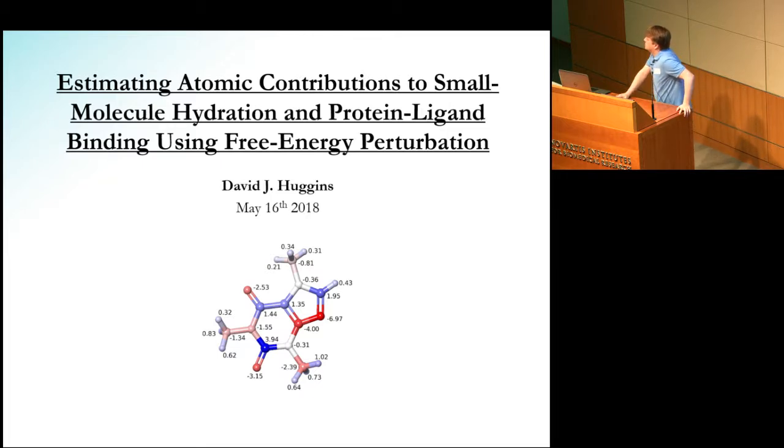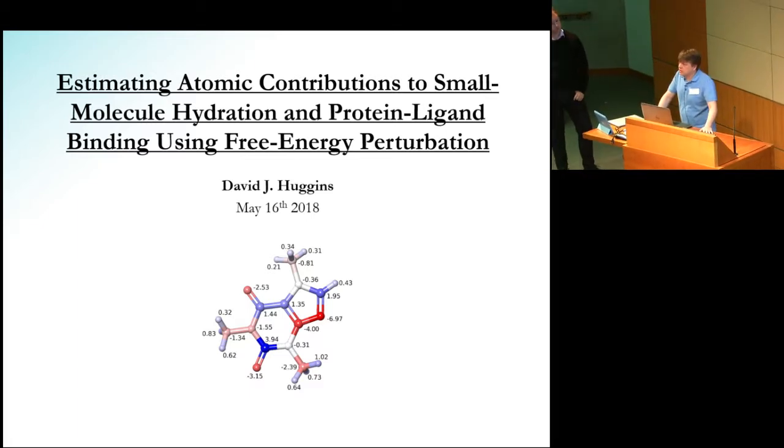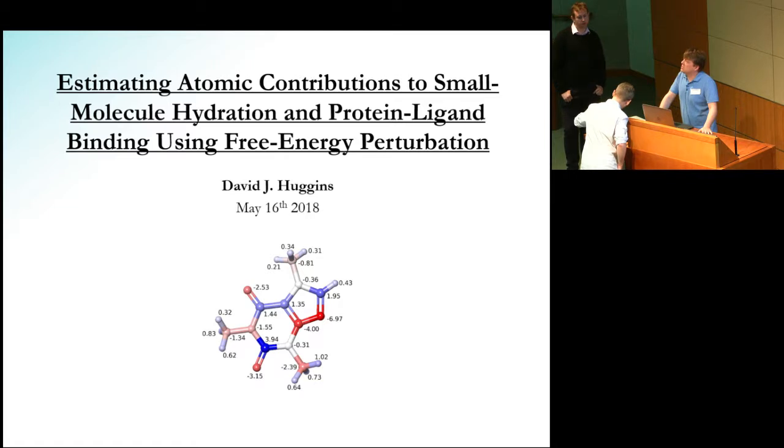Okay, just real quick for thermodynamics in the solid state. Could you make a comment on the importance of zero-point energies according to nuclear degrees of freedom, and also the importance of kinetic versus thermodynamic solubility? Excellent question. So in terms of zero-point energies, our comparisons between methods were done purely classically. The zero-point energy can contribute to expansion at low temperatures, but what we've generally found is that once you get above 50 Kelvin, it's irrelevant.